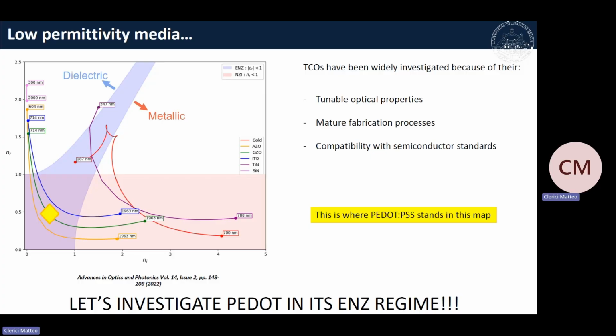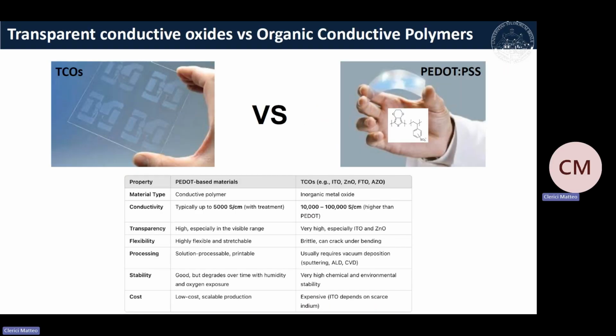So what we looked at was this map. Here you have the real part of the refractive index, here you have the imaginary part of the refractive index, and those blue, green, and yellow lines are our TCOs, so ITO, GZO, and AZO. And you see that PEDOT:PSS falls exactly in this region. So we said, well, let's see what happens with PEDOT:PSS. Now, of course, as with all things in life, you have pros and cons.